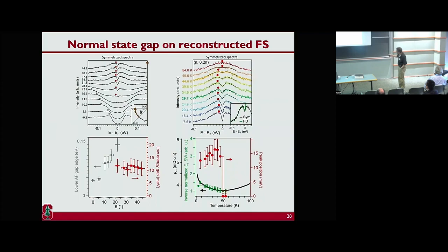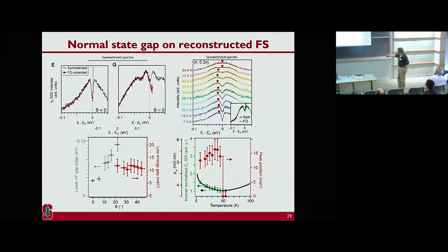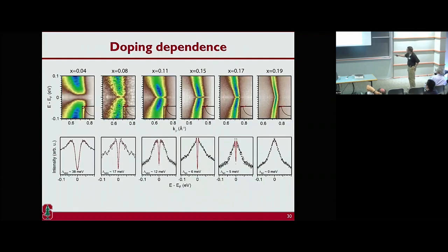And interestingly, if you look at this gap, and you take the data divided by the Fermi function, remember photoemission can study states above the Fermi level when they're thermally populated. You divide out and you look like this. Just to make a point, that again is the earlier data, at the antinode, if you divide things out, it looks like a particle symmetric gap. But if you look at the nodal region, there's also a gap. If you do the same trick, you can see the data going down. It's not particle symmetric. There's another type of gap. That's why we say this was influenced by antiferromagnetism. So all this suggests that we have an energy gap at a much lower temperature scale, and that's doping dependent.